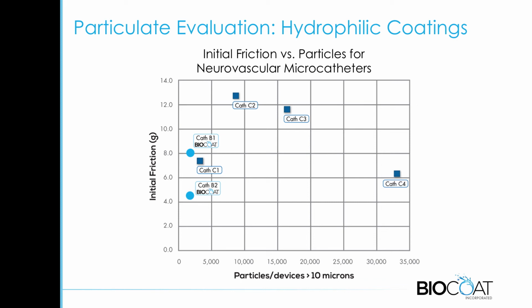Putting this all together, you can look at both the friction and the particulate generation on the same graph. And for this, it really differentiates between the various coatings. There are some that are low particulates but then higher friction. There are other ones that have a lower friction value but higher particulates. And that has traditionally been a trade-off between those two. Now with the best-in-class ones, you can have both. Lower is better on both, so you can have both low friction and low particulates.